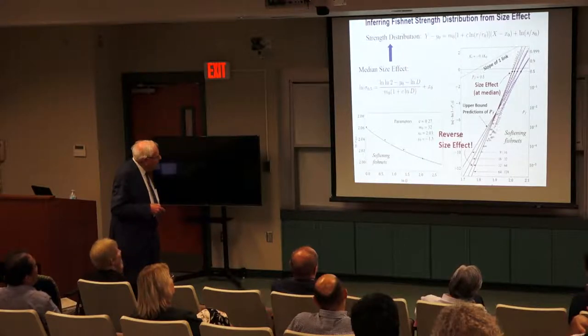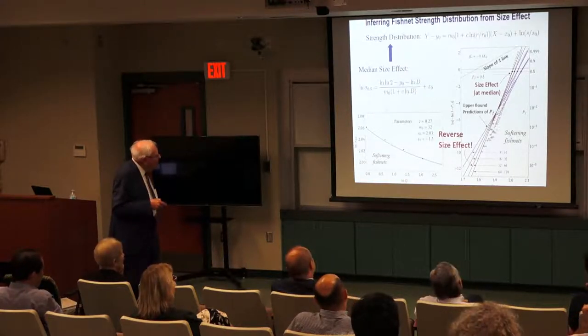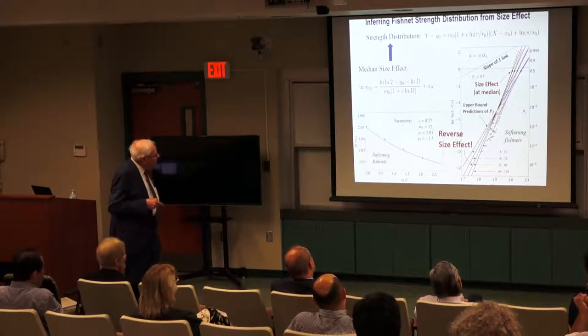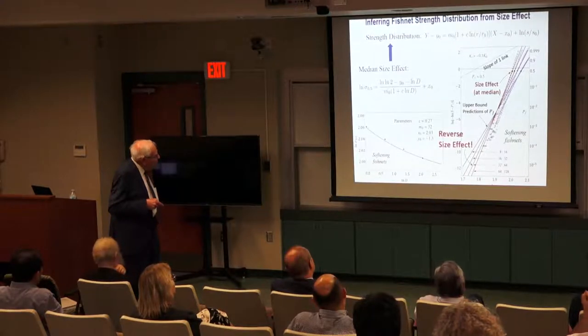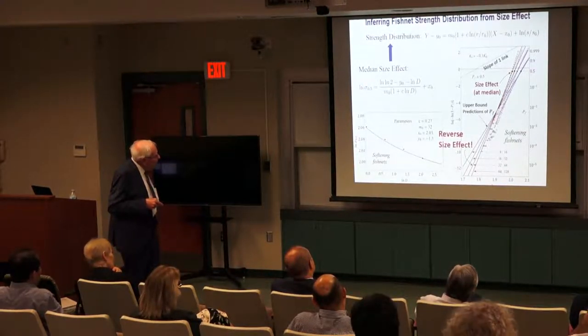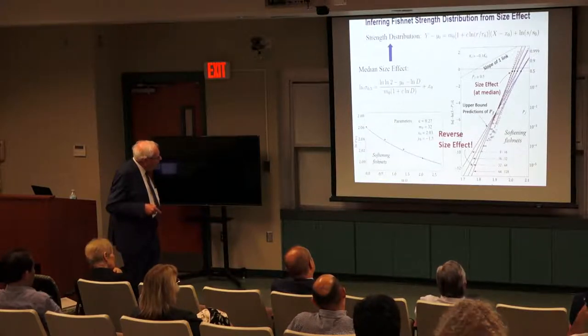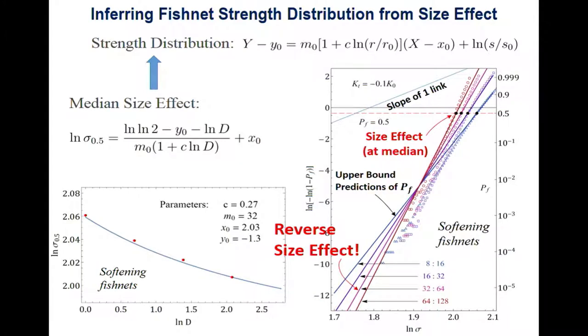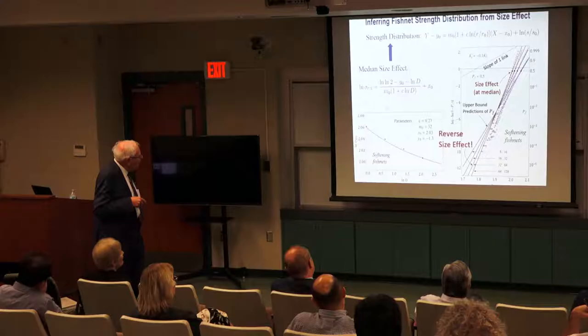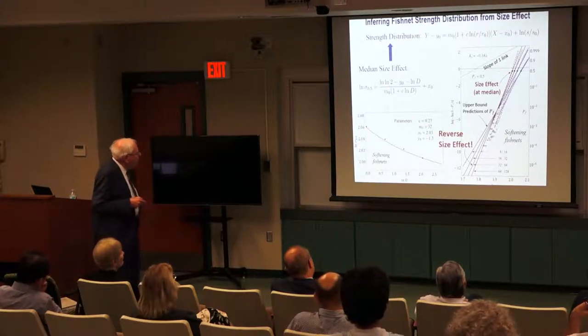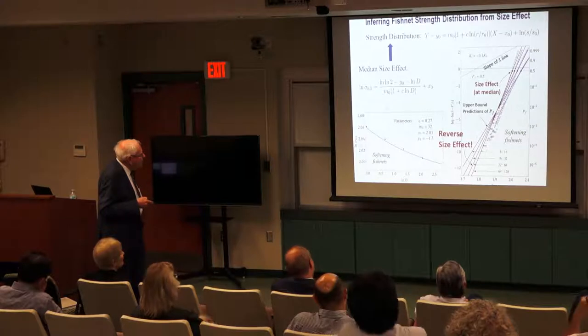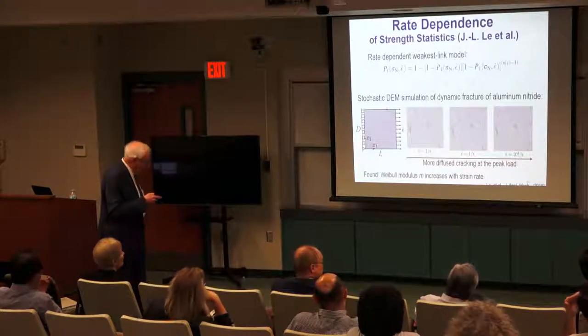Still there is an intersection point, but it goes to low probability, not being here, somewhere low. But it can happen, and probably often happens, that positive size effect in the mean, or this is median actually, you see the structure is getting weaker as it becomes larger, changes at 10 power minus 6, which would be, wait a minute, this is not probability scale, it's about here, you can have opposite size effect in the tail. So a structure which has a significant variation gets opposite behavior. And we can approximate a reasonably good formula for the median, sigma 0.5. We better fit the mean, where the mean is actually much harder, but they are close enough. So this is our latest work, which is just being published. We just finished a paper on this.